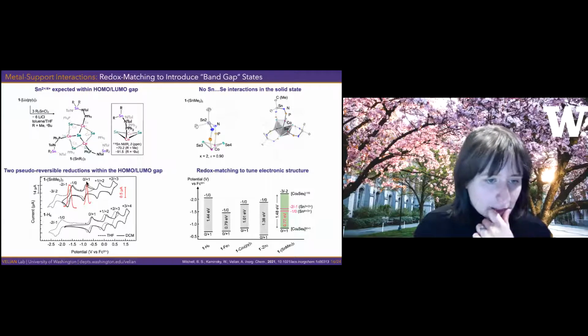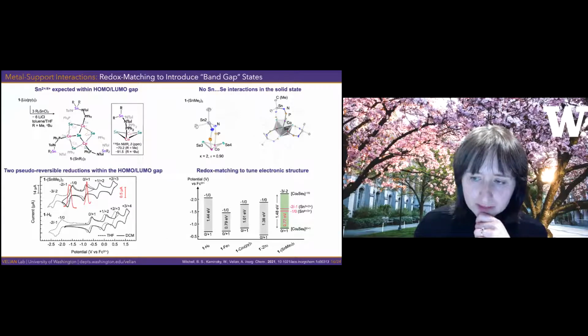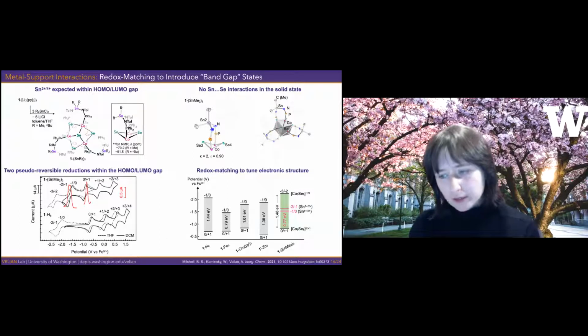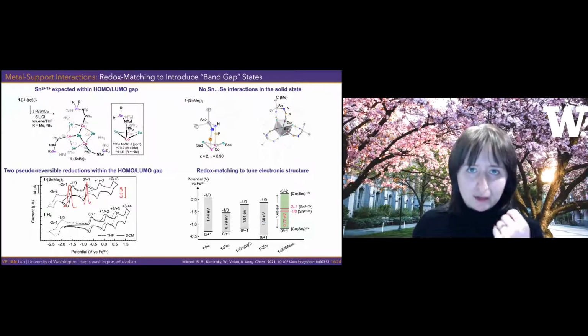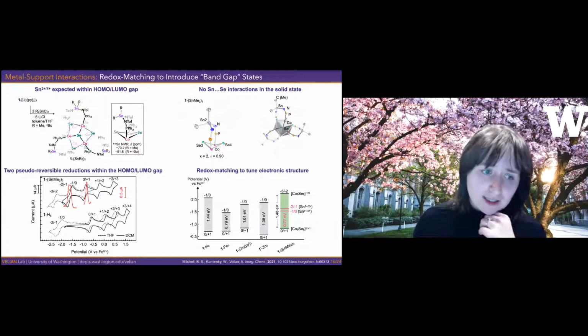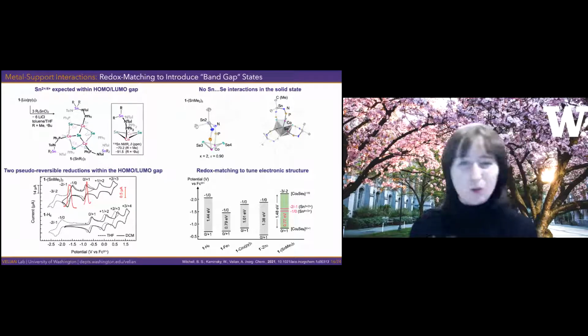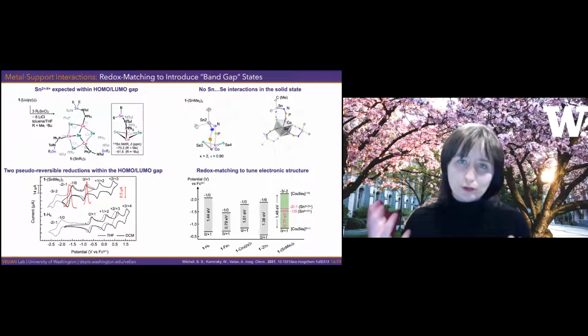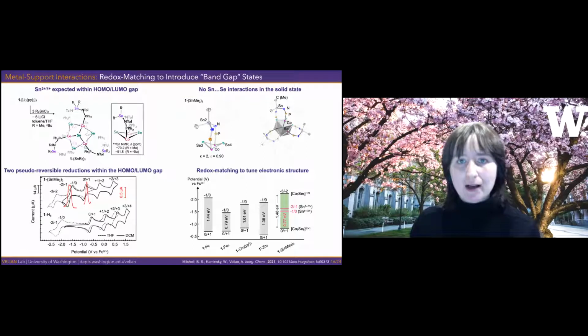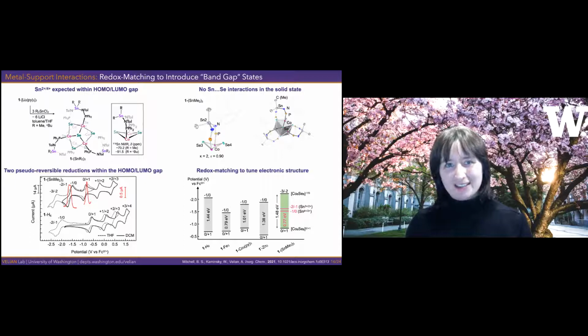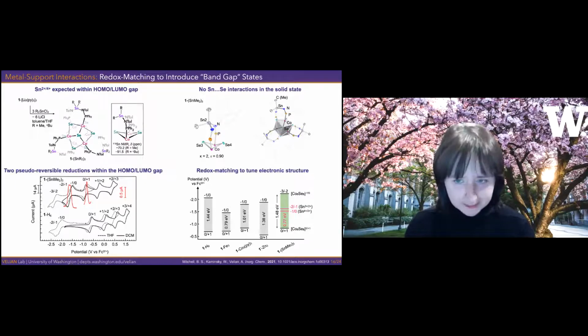And so in short, here's the first oxidation of the cluster, second, third, and how it compares to the free ligand. And now, compared to everything we've seen before, check out these two closely spaced single electron reductions that we believe are associated with tin 4 to tin 3 and tin 3 to tin 2 reductions. It was kind of surprising, but in a good way, to see that they are still chemically pseudo-reversible. But now we have a LUMO that is localized on an edge site, so no longer on the cluster core like all the other metals.